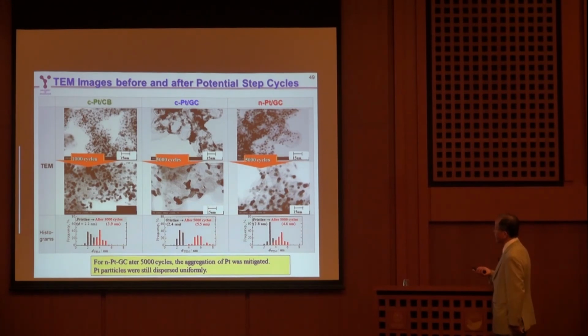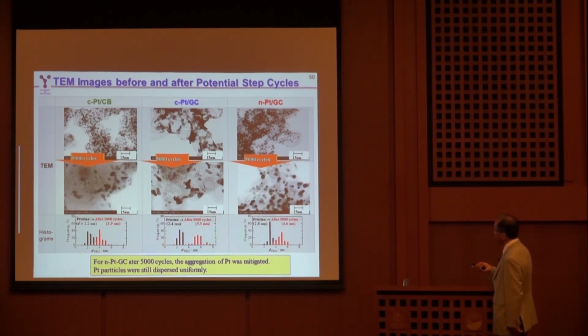And this is a picture after potential cycling, after 5,000 cycles. Both the commercial carbon black catalyst and graphitized carbon show a very big change of the supported catalyst. But our catalyst shows a very nice phase, even though the particle size grew.